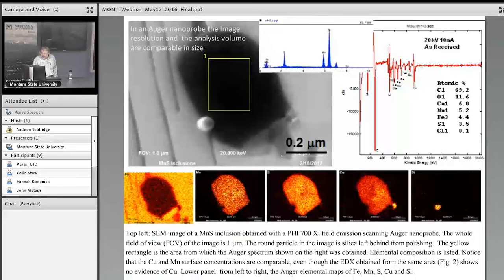And then this little one turned out to be a silica particle left behind from our polishing. So you see the resolution now. The whole thing is 1 micron, smaller than the size of a bacteria. Sometimes bacteria is too much. And you can get this kind of resolution. That's what we have upstairs.